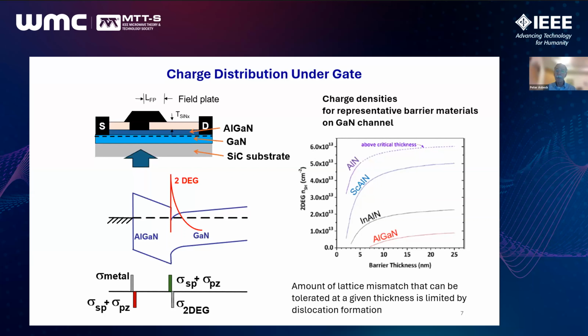The polarization charges and 2D electron gas densities can be very high, typically on the order of 10 to the 13 electrons per square centimeter, which is higher by a factor of 2 or 3 than obtainable in other 3-5 FETs. And the polarization charge can actually be increased substantially by changing the material for the barrier. And here are some simulations showing what can be done with aluminum nitride, and a lot of exploration today about the use of scandium aluminum nitride, for which the overall 2D electron gas density can reach 2 or 3 times 10 to the 13 per square centimeter. Of course, whether you can deposit these materials on the gallium nitride depends on the lattice mismatch between the different materials.